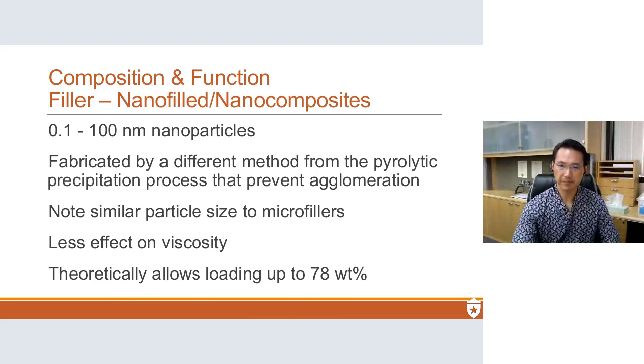The reality, though, is that really didn't happen, and you got smaller clusters. Better than the strands, but still smaller clusters of those particles. And those smaller clusters were still a problem because they're not chemically bonded, so they sometimes acted like holes and reduced the mechanical properties. So in reality, we didn't really get nanocomposites with discrete nanoparticles. It was still better than the microfill composites.